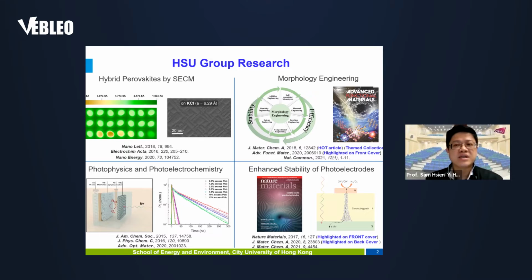Last year, we used heterojunction engineering to produce in situ formation of the heterostructure of the bismuth-based hybrid perovskite. This heterostructure of the bismuth-based hybrid perovskite leads to efficient charge separation due to the energy level alignment, for hydrogen production.